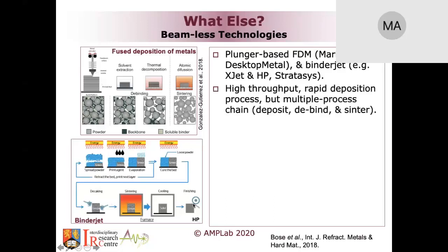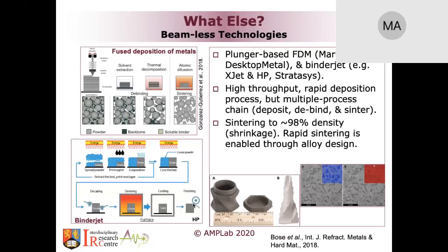The process is actually good. It can create dense tungsten. I've seen some reports from MIT where they were able to print good tungsten chromium alloys, but it has multiple steps: you deposit, debind and sinter. Some of the tungsten components, like the one I'm showing here, a tungsten chromium alloy, were fairly dense, made using beamless technology, without laser, without electron beam, only by a sintering type approach.